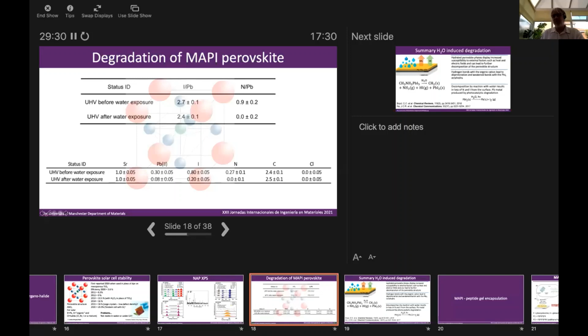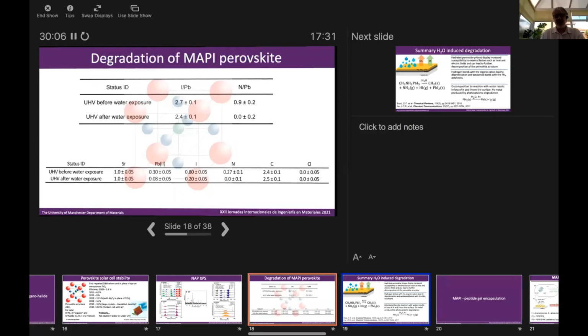Just to confirm as well, because we used a lead chloride precursor, we checked the chlorine content and we found there was no chlorine either before or after water exposure. So the conversion to methyl ammonium lead iodide was complete. Afterwards, as I said, the main change is a huge, complete removal of the nitrogen. The carbon content doesn't really change, which suggests that any carbon that is there is being converted from one form to another. And we see obviously a loss of the lead 2 compound, as it's converted to lead, as we saw in the previous slide, and a drop in the iodine content.